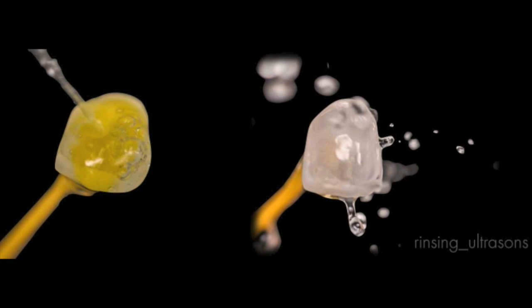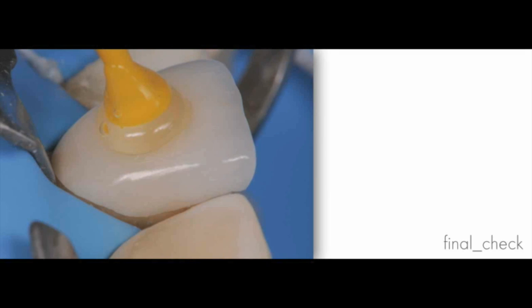So then we have to prepare the inner surface of the ceramic veneer. This veneer was made out of feldspathic ceramic, so I chose for the purpose 9% hydrofluoric acid applied for 90 seconds. Be very careful with this product, which is quite aggressive, and rinse it very carefully. Be careful with your eyes especially. And once it's done, excuse me, I like to do a final check.